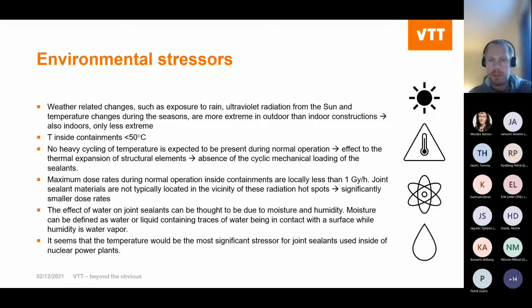Maximum dose rates inside containment are less than 1 gray per hour. But the sealant materials are not typically located in the vicinity of these radiation hotspots, so they face significantly smaller dose rates, and this was actually backed up by the data we obtained from Olkiluoto materials.